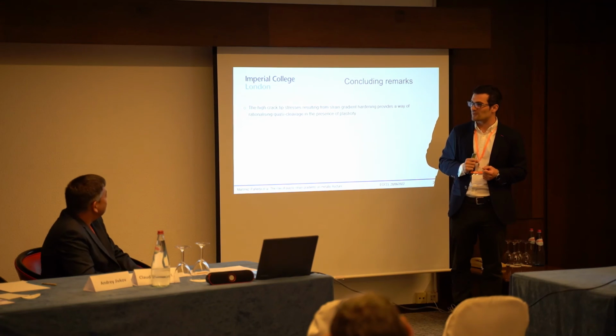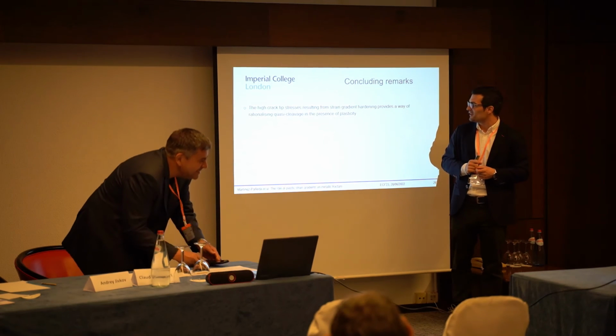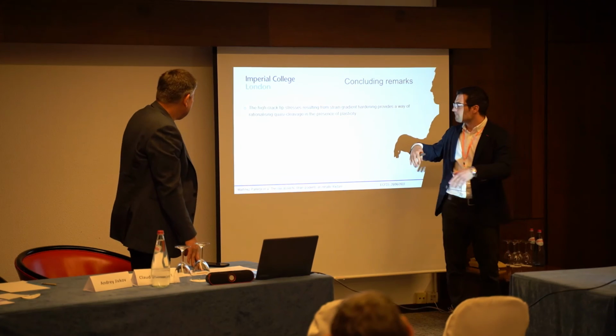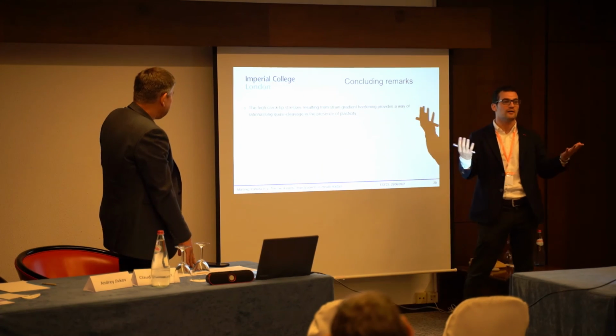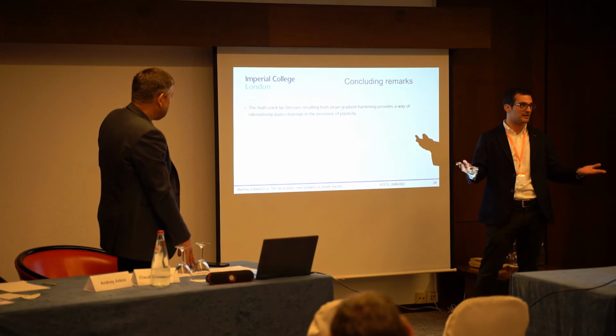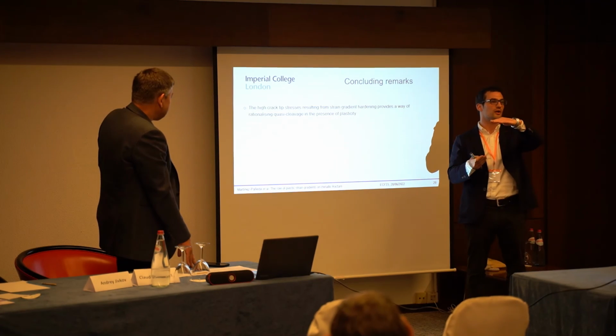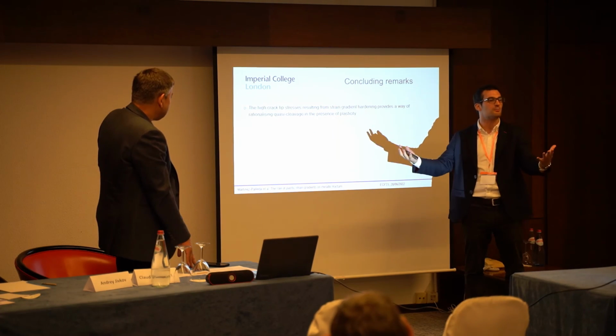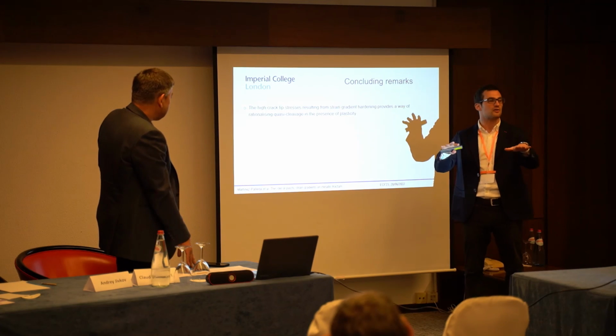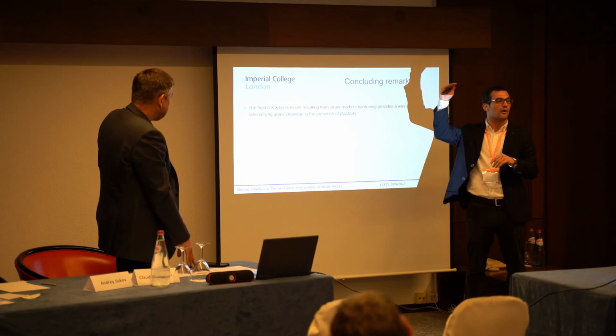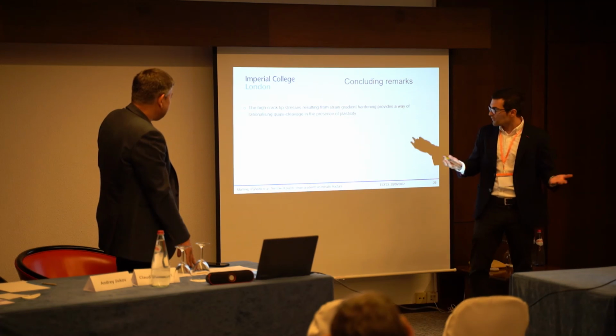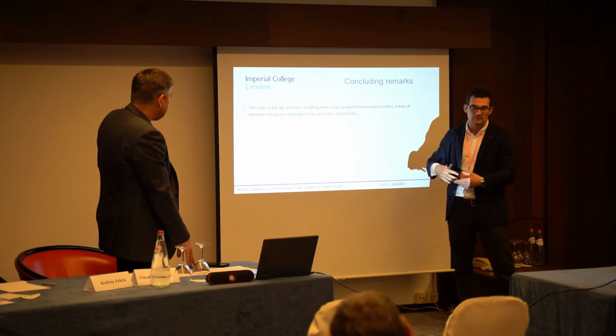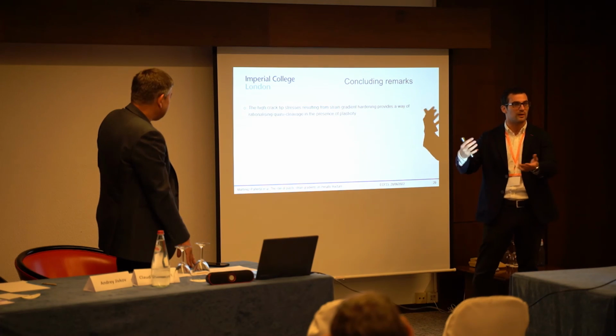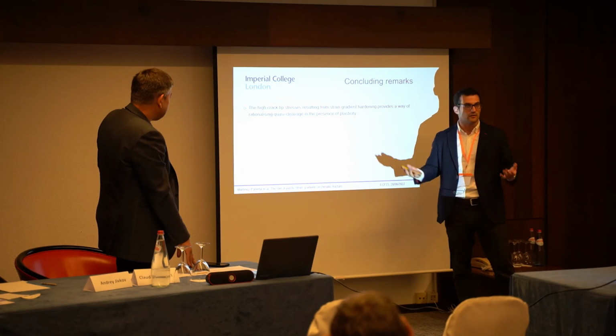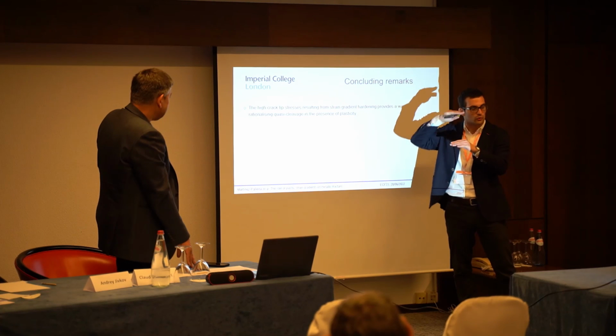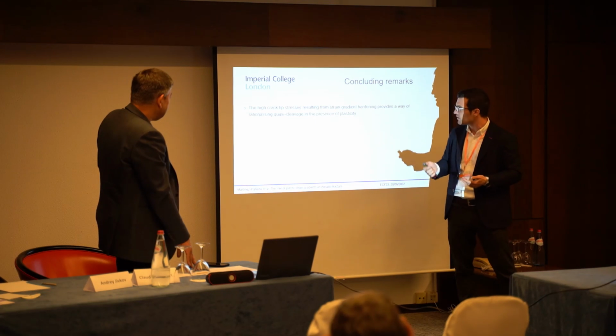So that's all. I hopefully finish the time with maybe one good question by saying that, I will just conclude by saying that, first of all, we need to understand why brittle fracture happens in the presence of plasticity. Plasticity is telling us that the maximum stress that you get is 4 times the yield stress, but we have a lot of experiments telling us that we observe very clean fracture surfaces, atomic decohesion processes, which require stresses of 10 times the yield stress. We think that the most plausible hypothesis is that strain gradient hardening, this additional hardening due to plastic strain gradients and GNDs, is triggering these high stresses that are enough to reach the quasi-cleavage strength under certain conditions.